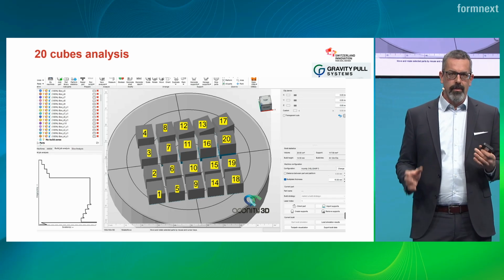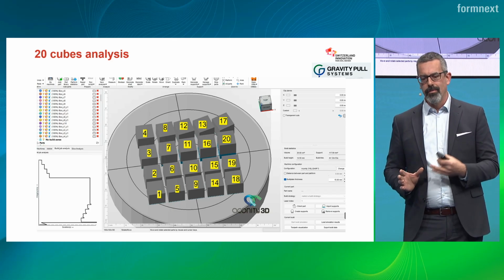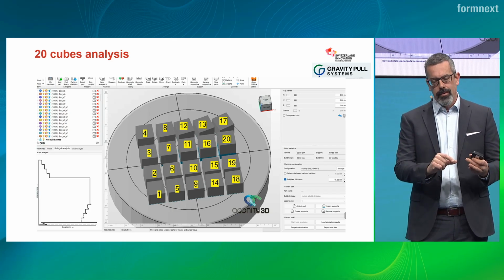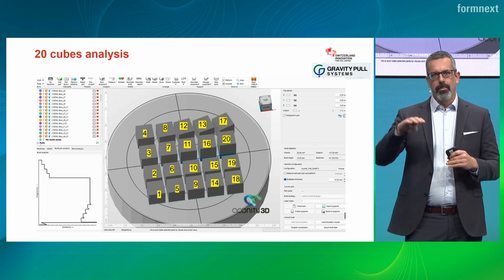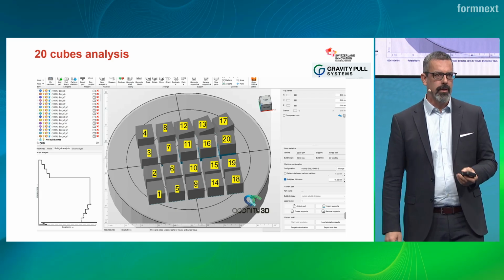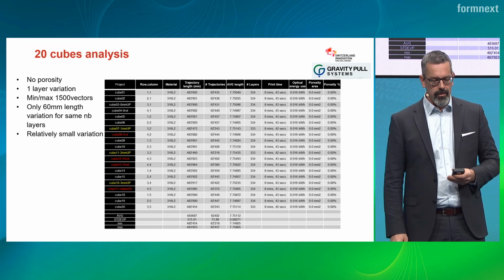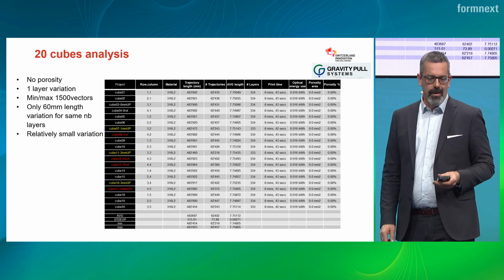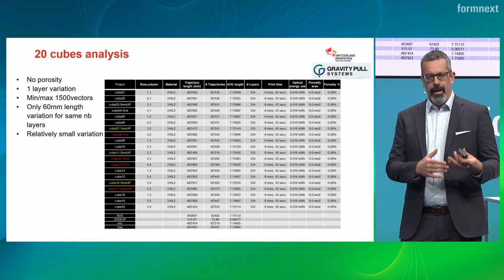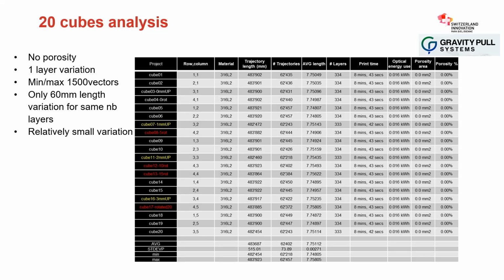Now we go one step further, and we place 20 cubes of the same kind on a platform. Different location, different angles, and some are on a higher support, so they shifted a little bit. So you would expect probably the same as me. So there is one table. I don't want to say a lot about it. You have a variation in the number of vectors that are scanned between the geometrically identical cubes of 1,500 vectors difference, 6 centimeters of difference in scanned total length, and surprisingly, one cube has 1 layer less. So the slicer output just makes the geometry 30 micron shorter, and I didn't know about this before.